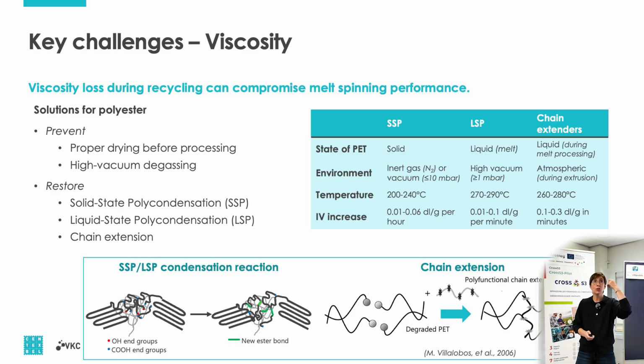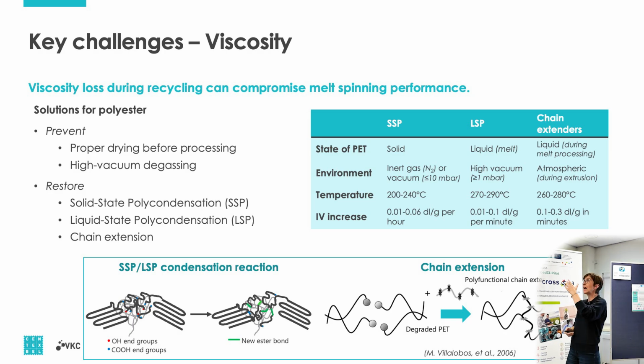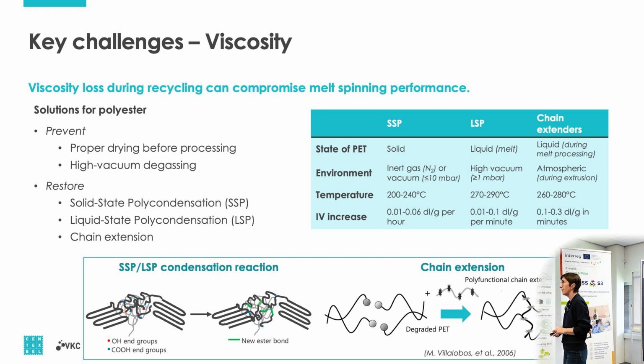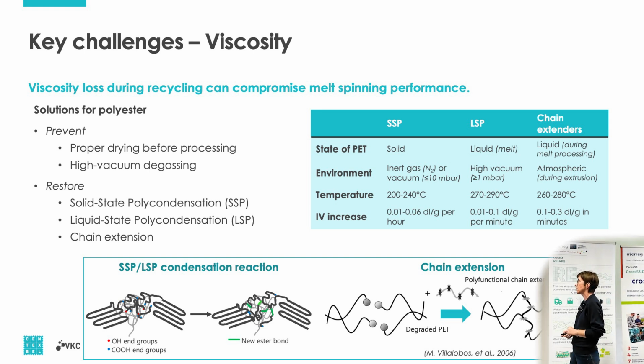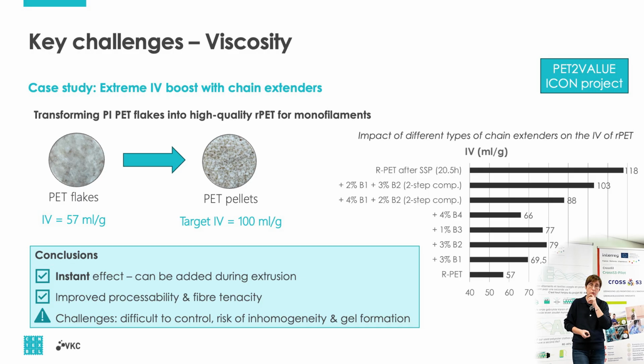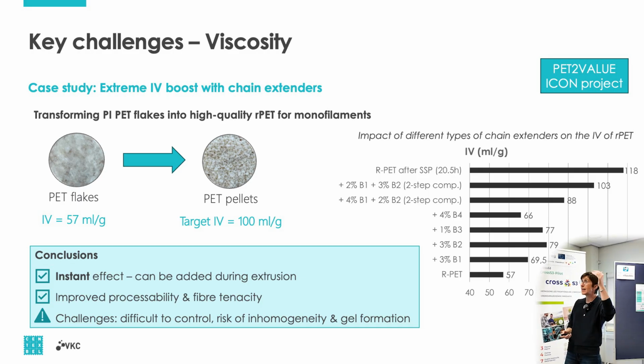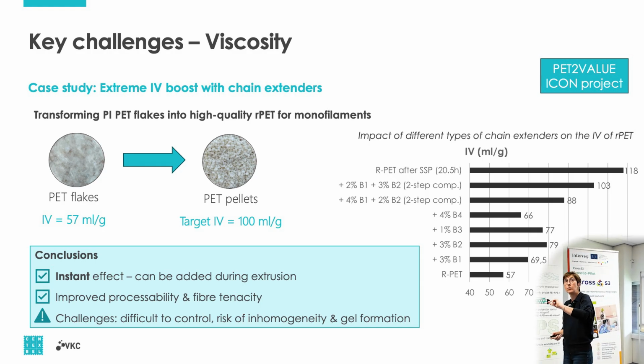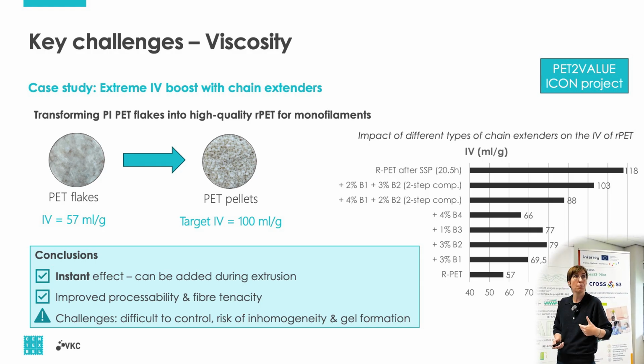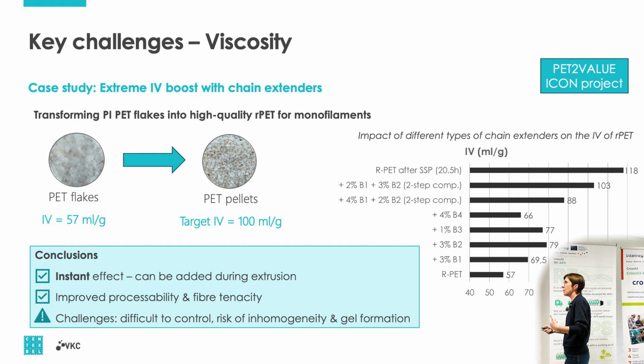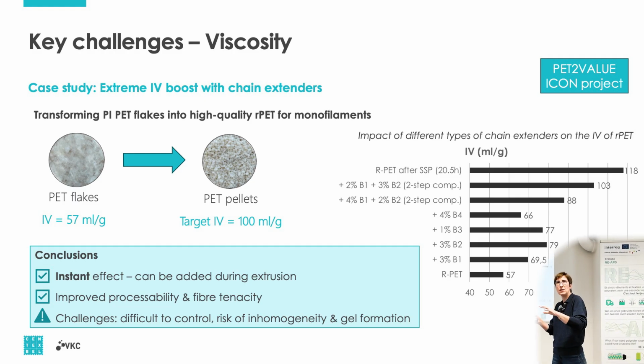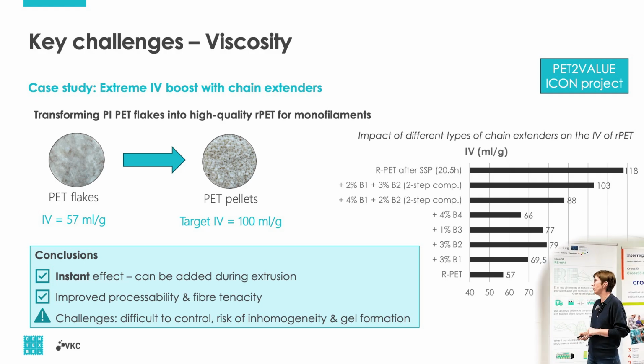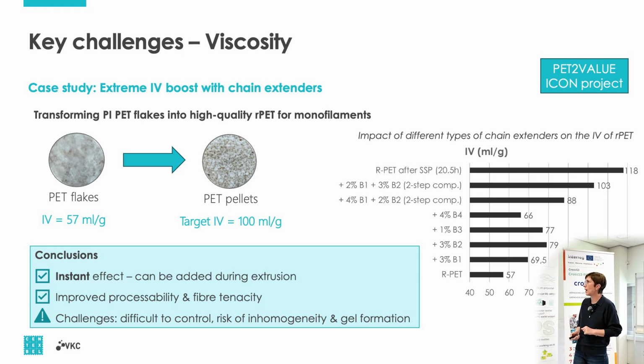This is how the machines are also reconsidered, especially for our textile materials, because it's very important to work on this IV enhancement of your materials. This is an example where we worked with chain extenders. The idea was to have again an IV of 100, which is already quite high. It will mean going back to high tenacity. For a classic monofilament fiber, we are aiming for something like an IV of 60, 65. Depending on your end application, you might need a different IV value. But here, the aim was to go back to an IV value of 100.